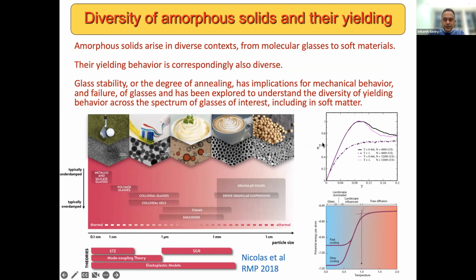What I show in the graph in the middle right is from computer simulations, the stress-strain curve of glasses prepared on the computer, one set of which are not so well annealed, and these show basically a gradual increase in the stress as strain is increased, going over to some flow value. In comparison, a better annealed glass exhibits an overshoot. So the stress goes up higher than the flow value, and then there's a stress drop going over to the flow stress value. A glass that is prepared by fast cooling will show the first kind of behavior, whereas a glass that is prepared with slow cooling will show an overshoot.